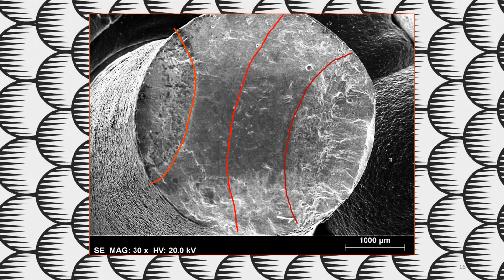Again, looking at an enlarged image of a fracture surface, we can see the change in curvature occurring halfway through the specimen, associated with the surface propagation that is associated with the residual stresses on the surface of the specimen, which has led to only surface to subsurface crack initiation.